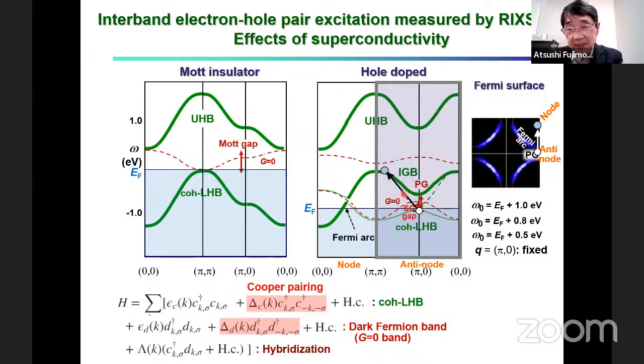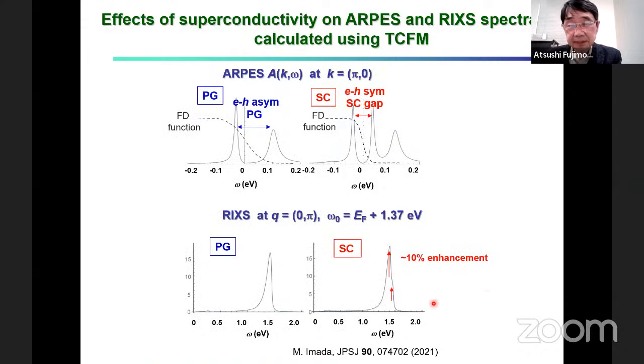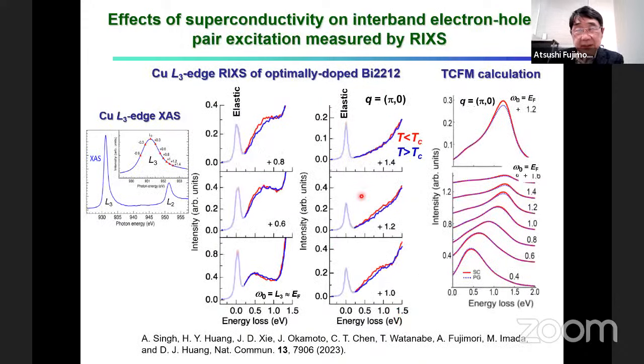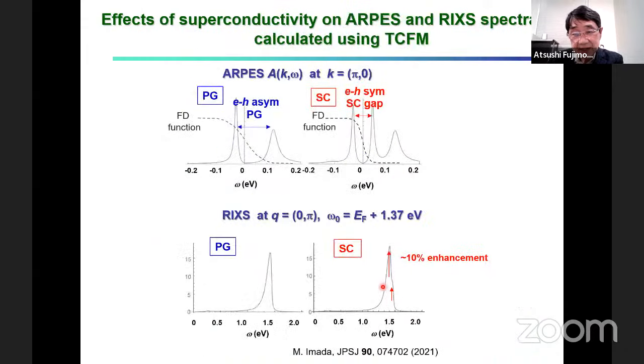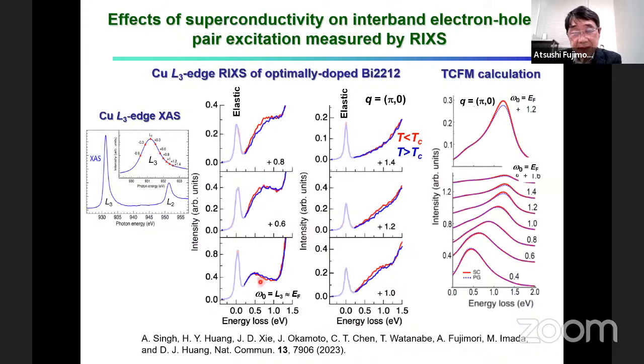But in energy momentum space, the excited electron energy is increased. Then according to this increase, the initial state also shifted. So basically, the raw data shows enhancement below TC, like this. As the incident energy is increased, the enhancement in the superconducting state is enhanced.